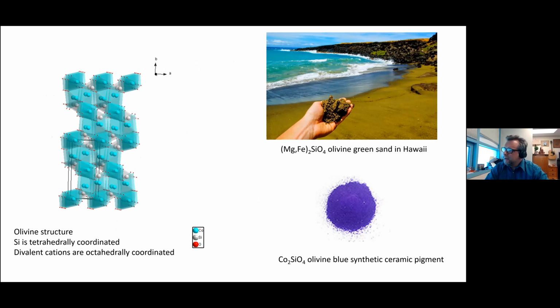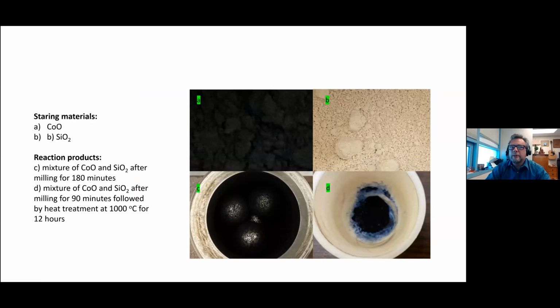So in Hawaii, we have a peculiarity. Some of the beaches have green sand, and it's actually olivine. It's just not cobalt olivine, it's magnesium iron normal olivine. The cobalt olivine blue pigment is blue in color, like you can see here. It has the same structure as the normal magnesium olivine forsterite, with cobalt residing in the iron sites. So we performed the experiment starting with cobalt(II) oxide and silicon dioxide as our starting materials.